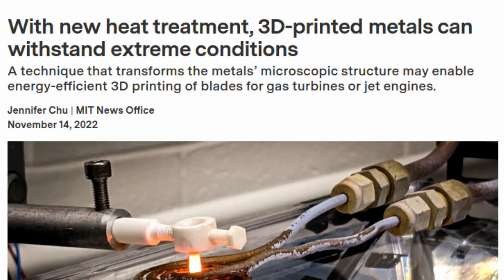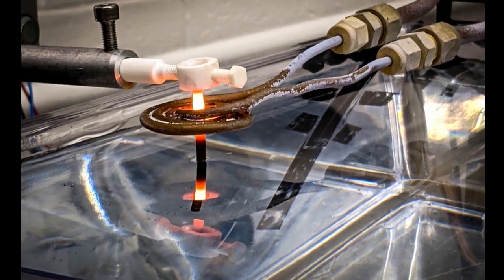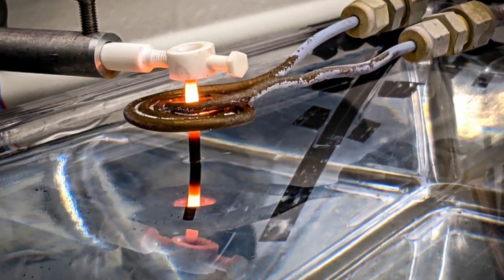MIT researchers found a way to improve the structure of 3D printed alloys by adding an additional heat treating step, which transforms the as-printed material's fine grains into much larger columnar grains, a steadier microstructure that should minimize the material's creep potential, since the columns are aligned with the axis of greatest stress.